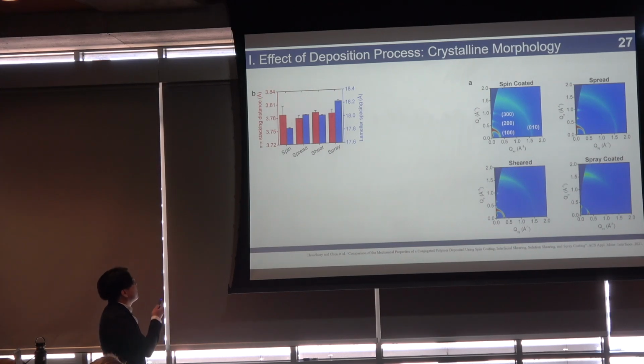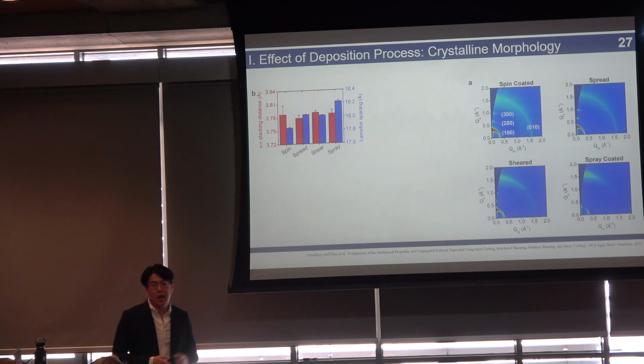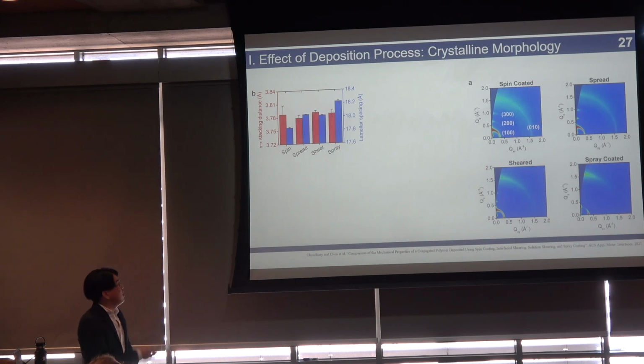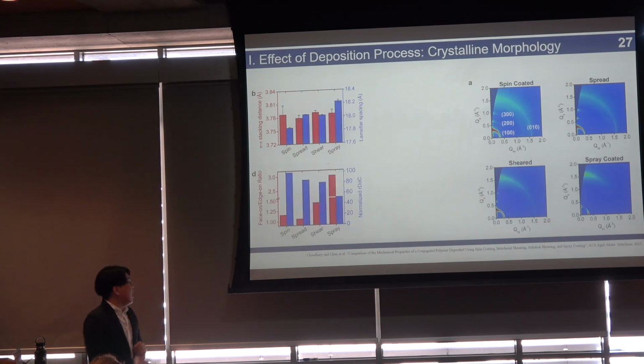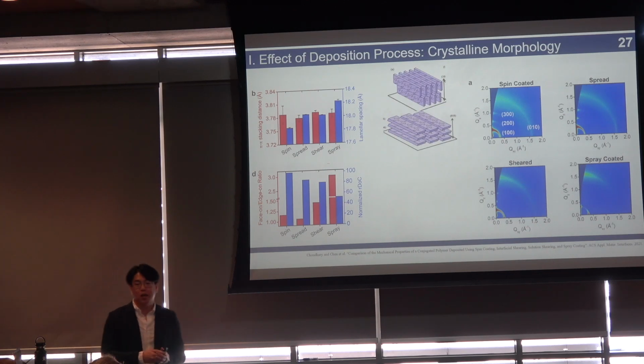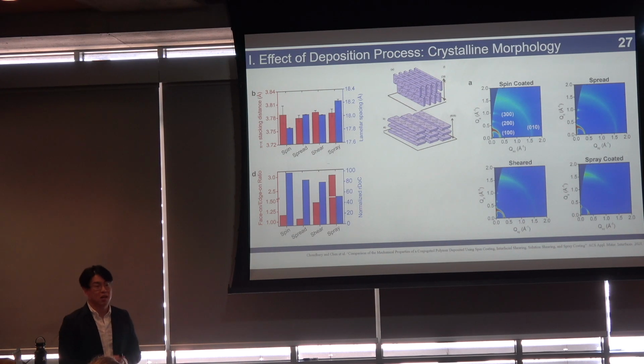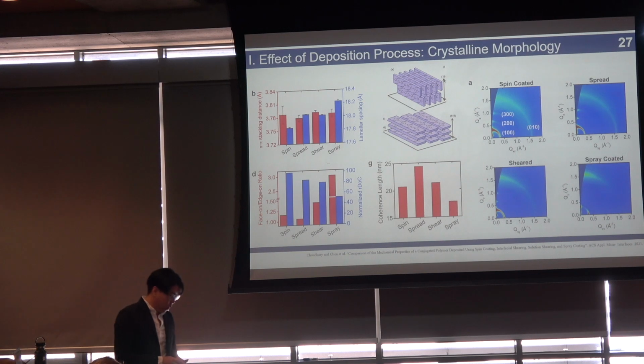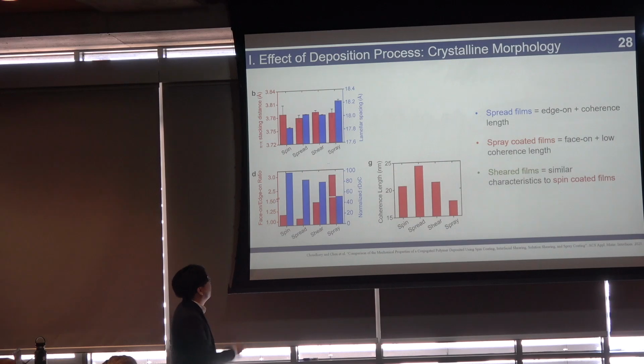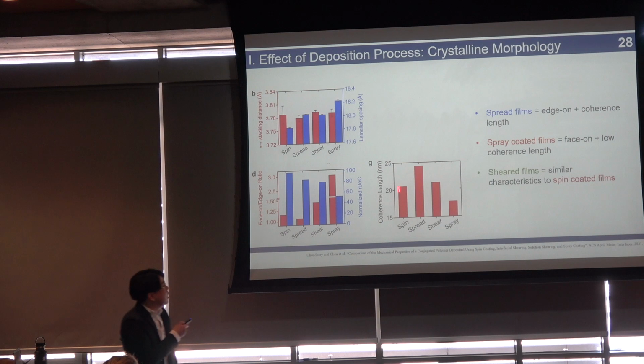diffraction images. For example, you can extract the pi stacking distance, which is how close the backbones are, or the lamellar spacing, which is how far apart these side chains are. You could also extract the texture of your material, whether it's face-on or edge-on. So by this, we mean whether the side chains are pointing up vertically or whether they're pointing parallel horizontally to the substrate. And we can also extract the coherence length. So from here, we see a couple different things. First and foremost, spread films have a very, very high edge-on fraction, and they have a very high coherence length. Spray-coated films are the complete opposite.